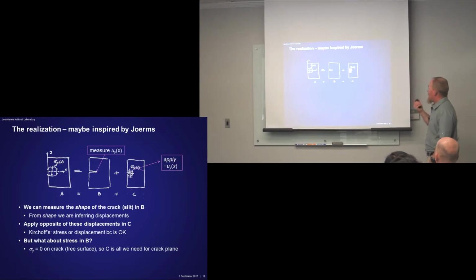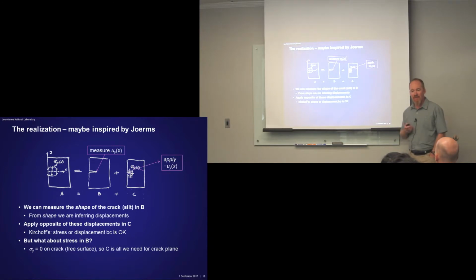Also, this is the point when I had the idea that I could do something different. This is that first line of the superposition principle, where you're superimposing stresses, right? I was thinking maybe about that Jorm's paper, but if you measure the shape on that cut face, could we apply, instead of a stress, a displacement here, force it back flat displacement-wise, and get back the stresses? And I thought about that, and there's no reason that shouldn't work. It's a Kirchhoff boundary value problem. You can swap out stresses for displacements for a boundary condition. Should work totally correctly.